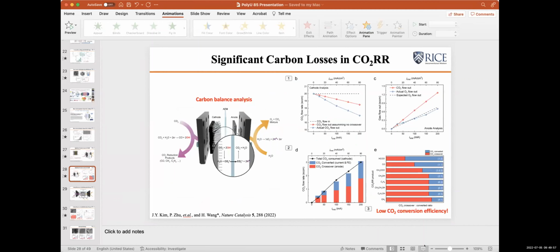Well, that's a great question. I think there are two levels of challenges here. Of course, with crossover, you will have a lot of carbon loss. And also crossover could introduce some instability of the membrane, because we know that a lot of the anion exchange membranes, especially for hydrogen fuel cells, alkaline fuel cells, don't like CO2, right? If you have some CO2, there could be carbonate that gets stuck inside the membrane, causing ion conduction instability. But there are a lot of new companies that recently developed different ion conductors specifically designed for carbonate. So the stability issue for the carbonate crossover has been significantly mitigated. Some recent work demonstrated 1,000 to 2,000 hours of continuous operation for CO2 reduction. So I don't think crossover in some specifically designed membranes is a big challenge.